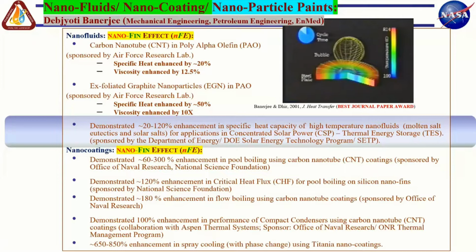And our computer model predicted that if you can enhance the thermal diffusivity of your heater surface, the cold spot will be wider, which makes sense. And so by that token, we said, okay, if you put nanotubes in there which have high thermal diffusivities, it should enhance the cold spot. That was the angle with which we were doing the experiments. But we were not really sure how much of the enhancement was coming from the higher surface area caused by this nano coating.